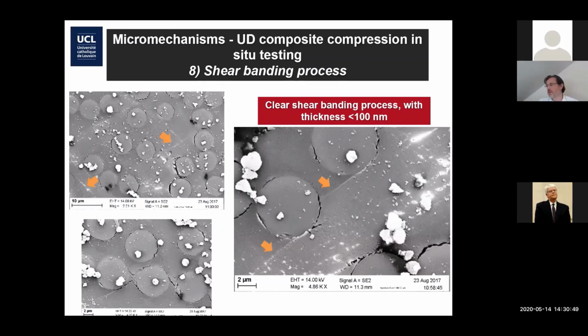And a final experimental result I would like to show is the following. These are now tests on composites with aligned fibers. It's a compression test on a UD composite. And the reason I'm showing it is not to look at this nice fracture event. This is not my purpose. The purpose is that we very distinctly see a shear banding process. There are many examples of nice shear bands that are observed and which later on developed into a damage localization. But at the beginning, it's a very distinct shear banding process. And we see it very well in this composite configuration. Typical thickness is way below 100 nanometers, but we cannot measure accurately. But there is definitely a shear banding process.